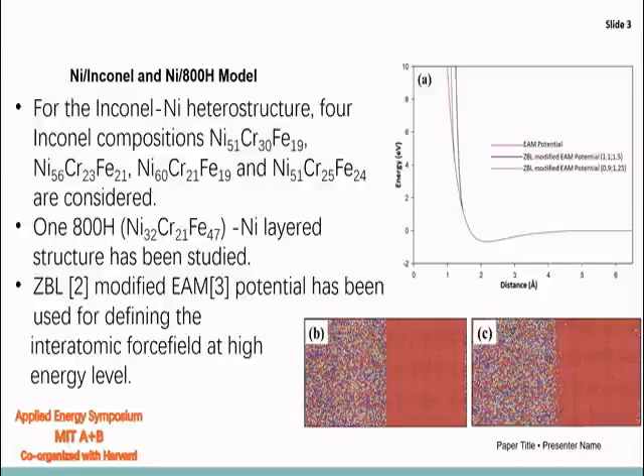In this study, we have investigated different compositions of nickel Inconel multimetallic layered composite, and we also investigated the 800H nickel structure. Here are the Inconel compositions that we have used, and we have also used the ZBL-modified EAM potential to define the interatomic interaction at a very high energy during the cascade simulation. Here we have introduced a primary knock-on atom energized with 10 keV energy to initiate the cascade at a high temperature of 1000 Kelvin. We have used the successive cascade algorithm to reach up to a DPA level of 0.5.